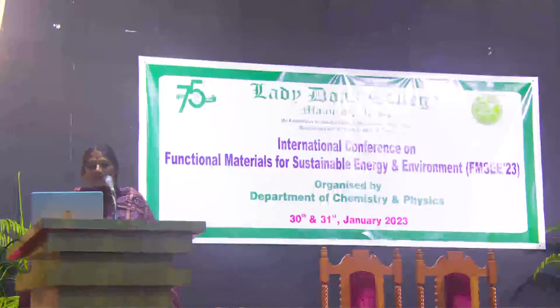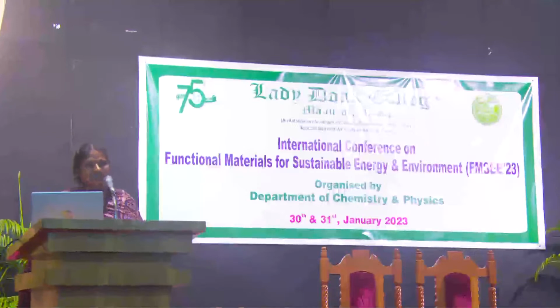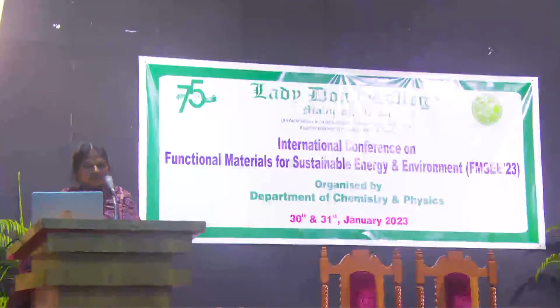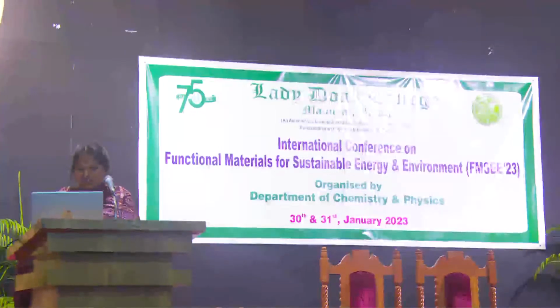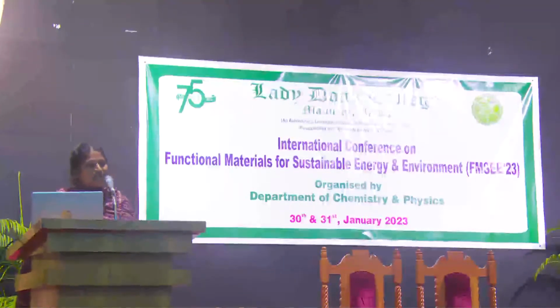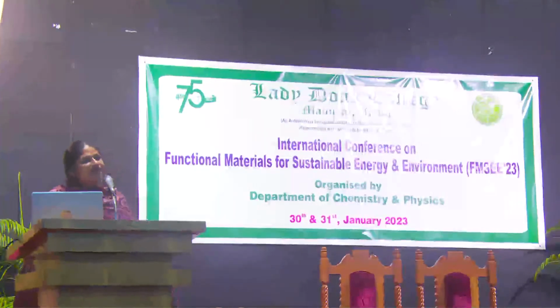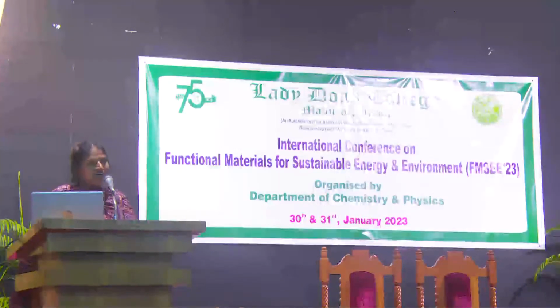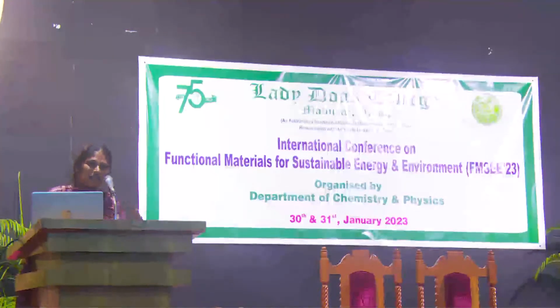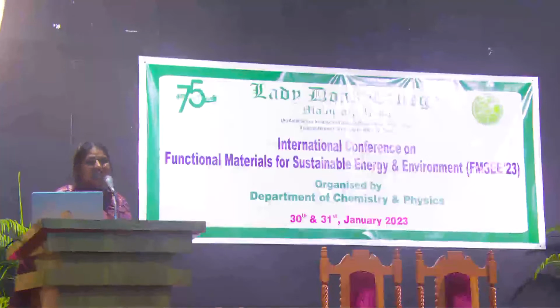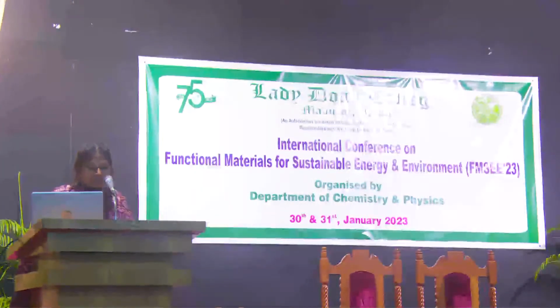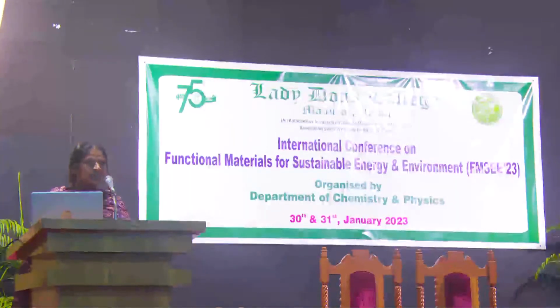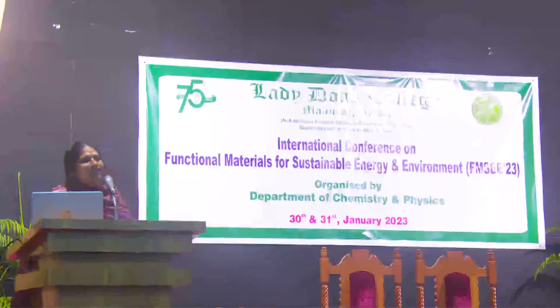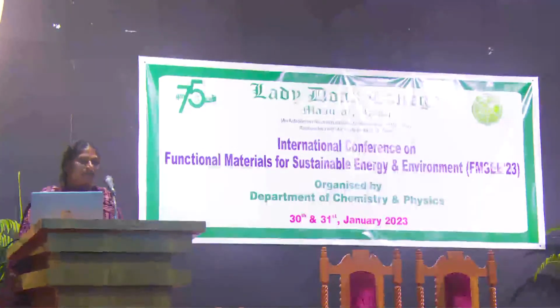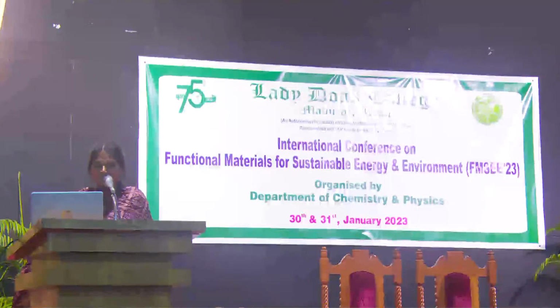And the United States Department of Energy has fixed some targets for host materials: gravimetric density 5.58% and volumetric density 40 gram per liter. So based on this, I have adopted jackfruit seed as my host material. Why I adopted it: in southwest Tamil Nadu, in Palapalam, because people demand the fruit, it is harvested prematurely and dumped into landfill. It gets wasted, and the edible part of the fruit is only 25 to 35%, with the remainder being waste. In that aspect, I have adopted this as my material. And the seed also has a naturally water absorbent property, so it might act as a good absorbent material.